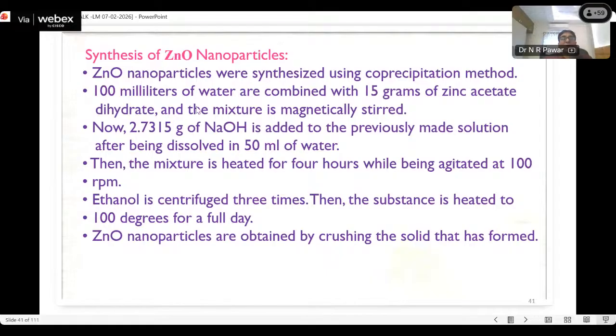Now 100 ml of water is combined with 15 grams of zinc acetate dihydrate, and the mixture is magnetically stirred. Now 2.7315 grams of sodium hydroxide, after being dissolved in 50 ml of water, is added to the previously made solution. Then the mixture is heated for 4 hours while being agitated at 100 rpm. It is centrifuged 3 times with ethanol. Then the substance is heated to 100 degrees for a full day. Then ZnO nanoparticles are obtained by crushing the solid that has formed.